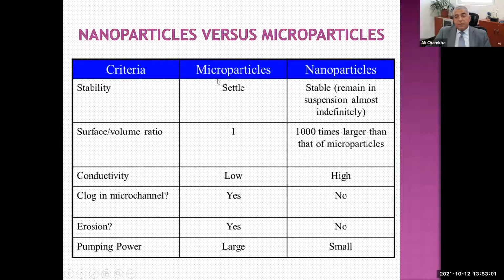If you look in terms of stability, microparticles settle in the flow when they are suspended in a fluid, while the beauty about nanoparticles is that they are stable and remain in suspension almost indefinitely in the fluid. Surface to volume ratio, it is 1 for microparticles. It's 1,000 times larger than that of microparticles for the nanoparticles. Thermal conductivity is low for microparticles, high for nanoparticles when used in fluids.